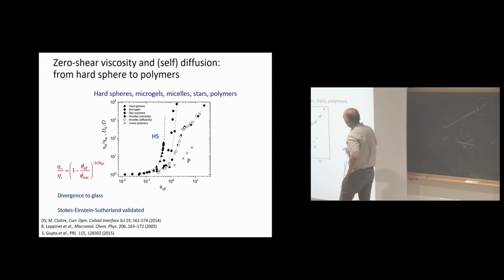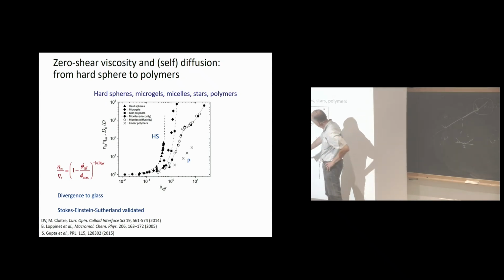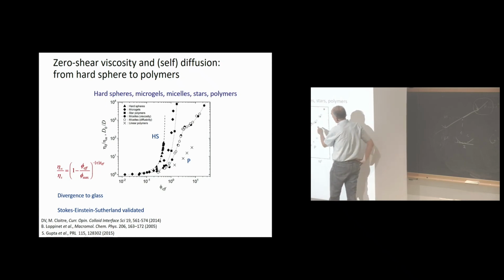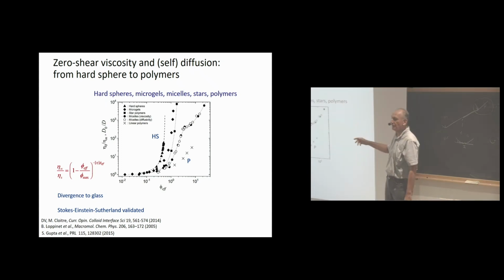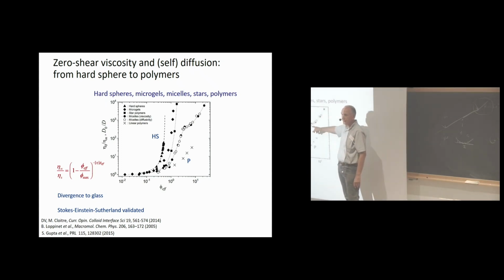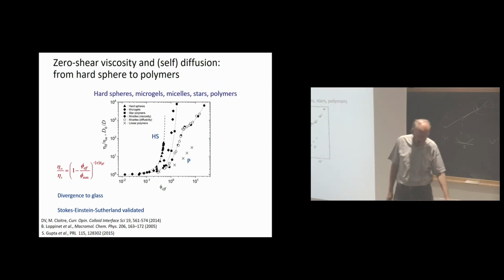And the point is that this is now viscosity and diffusion together for soft particles, okay? So this is hard spheres, this is polymers, and this is different soft spheres. A point to make is look at this. This is a particular class of grafted microgel particles, right? Okay, so why does this happen? And this also agrees with simulations. Can you think why you have this bump here? You have osmotic compression of the particle, because as you increase the concentration, the osmotic effects become more important, right?